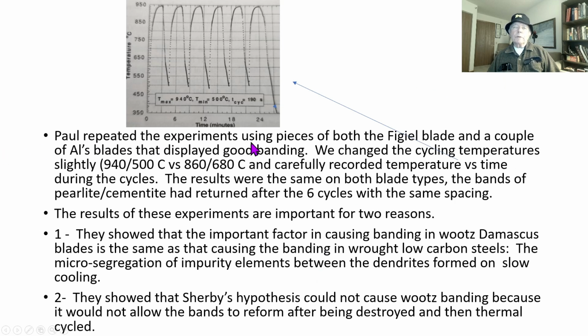Paul repeated those experiments using a piece of both the Figiel blade and a couple of Al's blades that displayed good banding. We put a thermocouple in so we could measure the temperature variation, and that was the result. The results were the same on both blades. The bands of pearlite, cementite had returned after the 6 cycles, and had the same spacing as original.